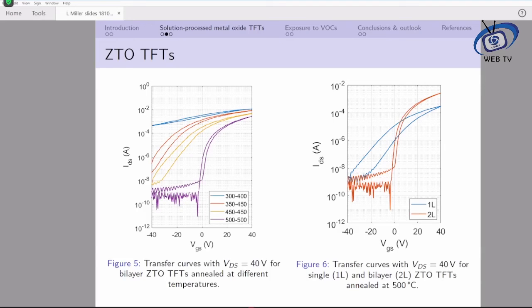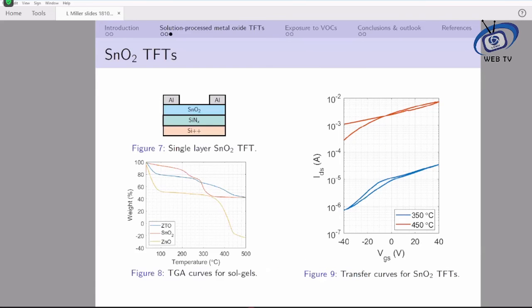The performance of single-layer and bilayer ZTO thin film transistors with all layers annealed at 500 degrees Celsius is shown in Figure 6. Hysteresis is significantly reduced with the addition of a second active layer, and the electron mobility achieved is the highest reported to date for solution-processed ZTO TFTs at 9.49 centimeters squared per volt per second. Next, I chose to fabricate tin oxide thin film transistors to compare against the literature, and tin oxide is also an ideal material for oxygen-related gas sensing.